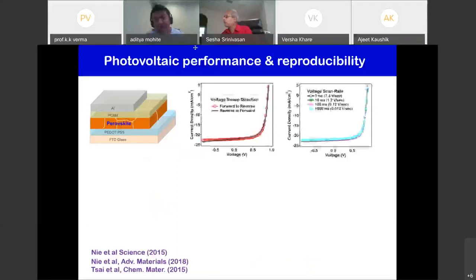What we were able to show is very reproducible performance. Here I'm plotting the current density as a function of applied voltage. One of the issues with the perovskite community was that there was a lot of strong hysteresis before this time. Here we were able to show that we don't see any hysteresis in these devices. You can do that as a function of scan rate and you'll see that this hysteresis is very negligible.